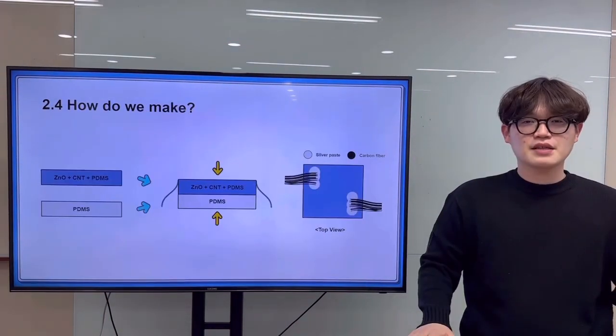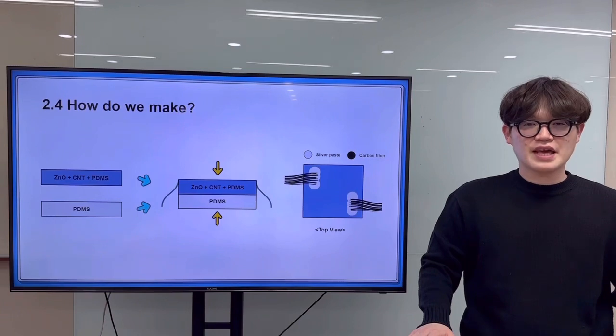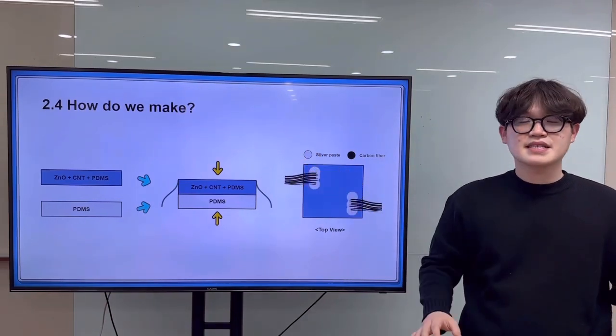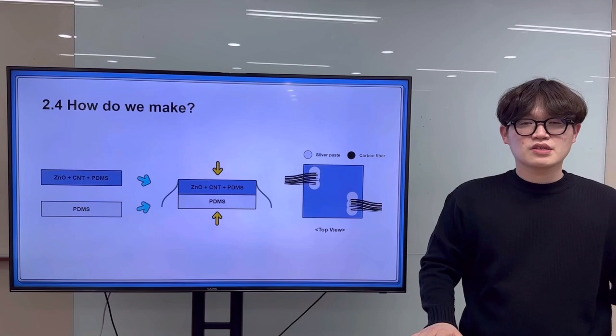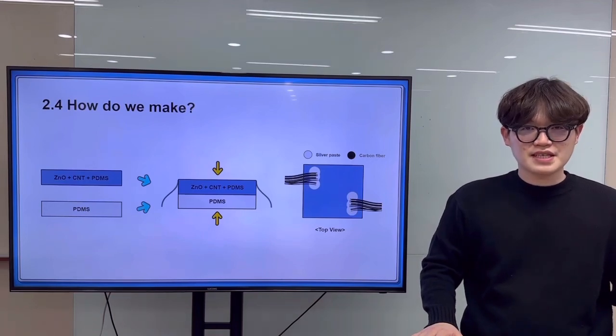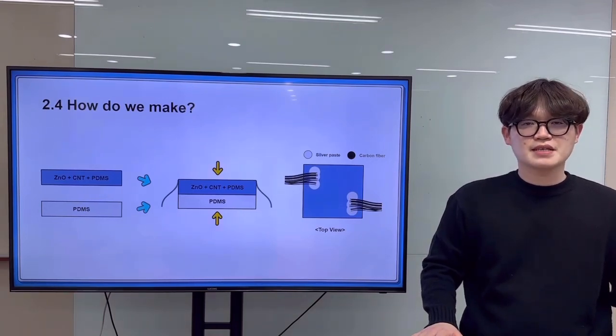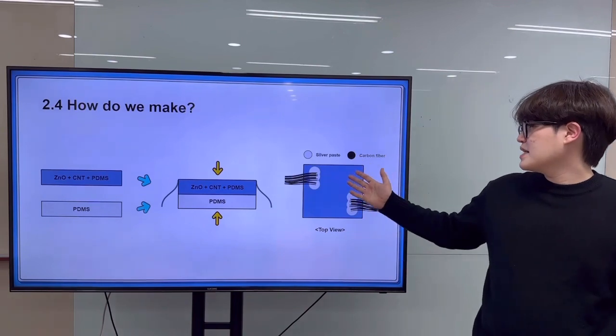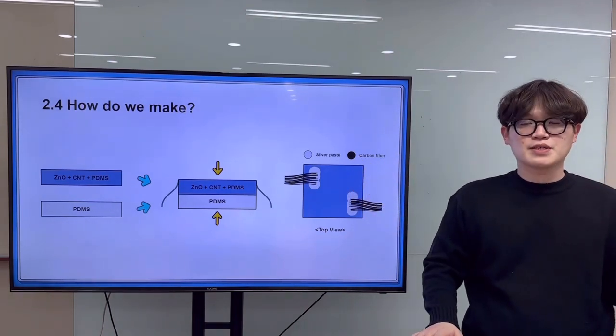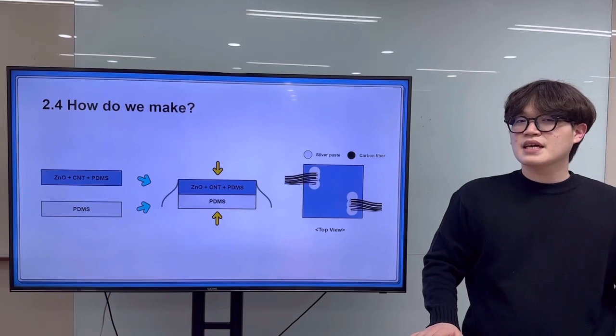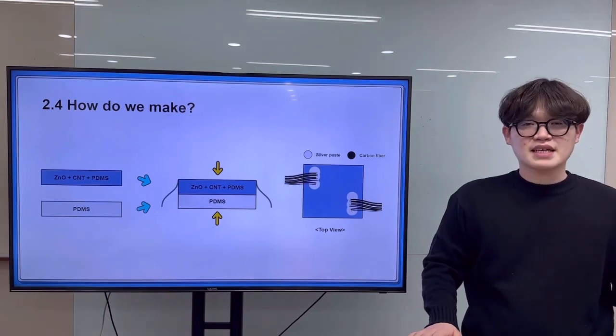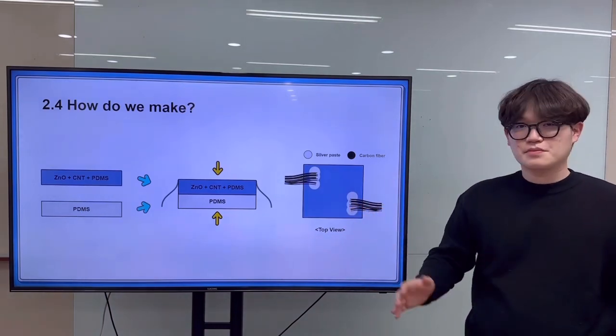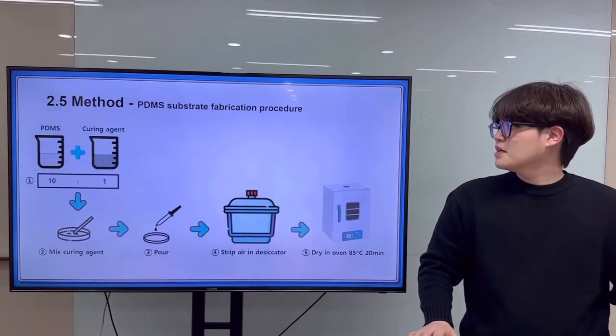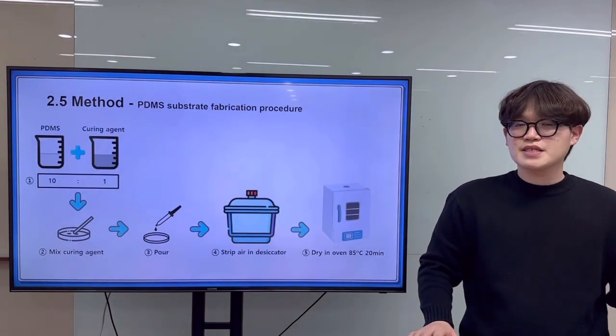Hi, I'm Jiwon. First of all, we decided to make a layer mixing zinc oxide and CNT with PDMS. The core of our device is flexibility, so we chose PDMS, known as a typically flexible material. In addition, silver paste and carbon fiber were used for post-processing, and we intend to make electrodes with a top view structure. Next, I will explain the substrate procedure.